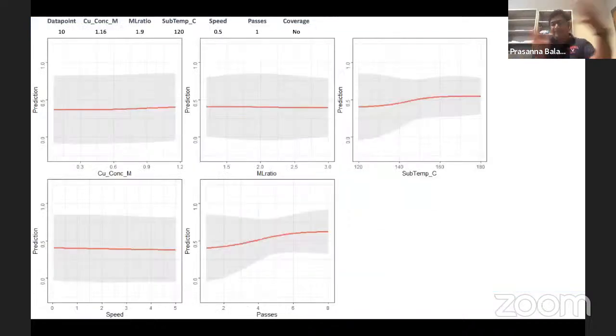So to map it back to the processing example that I talked about, this slide is not as pretty as the previous one, but I think it captures the story, right? So there was one data point, which we call data point number 10. These were the specific numbers that we used to make this particular composition, okay? This particular experiment resulted in a thin film that lacked full coverage, okay? That's why you have a no here, right?